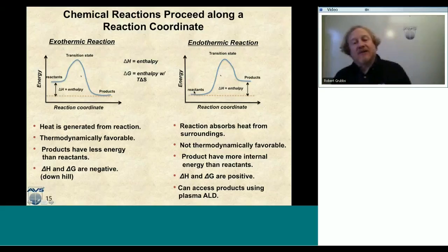Now, endothermic reactions, you can see here that products are actually in a higher energy state than reactants. And so the enthalpy of reaction is actually positive, meaning that the reaction is not spontaneous and that we actually have to put energy into it or pull energy in from the surroundings to get it to go. We still have a transition state that the reactants have to go through. And when we use atomic layer deposition, we really can't access these product states through ALD. But if we use a plasma, which is a very energetic gas, we can make products that are part of an endothermic reaction in atomic layer deposition. So that opens up a whole new material class of compounds that we can make.